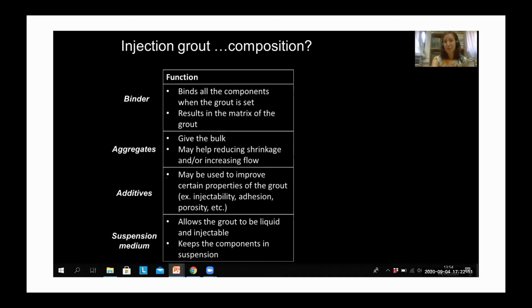So what's the function of these different components? The binder, as we said, binds all the components when the grout is set, and results in the matrix of the grout at the end. Aggregates give the bulk and may help reduce shrinkage or increase flow. So we'll see that according to the aggregates, which are chosen according to the particle size and shape, we may be able to achieve different properties. But aggregates are always needed in an injection grout.